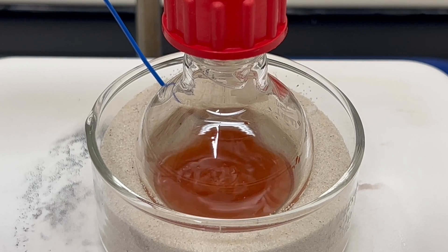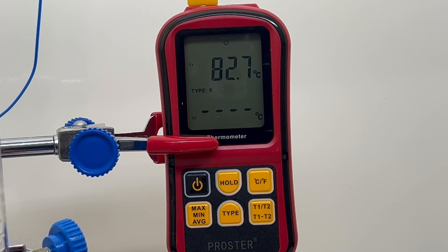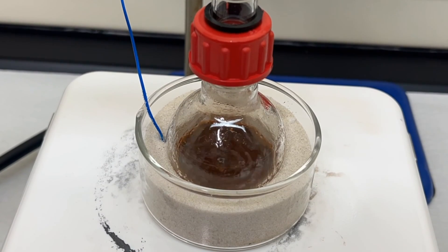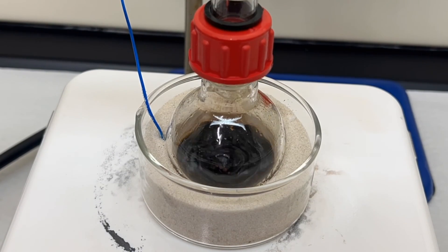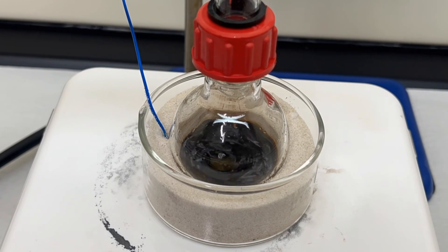After an hour the hot plate is slowly ramped up to 160 degrees Celsius and held for at least six hours allowing reflux. I had to head home so I let it run overnight. By the time I returned over 12 hours had elapsed.